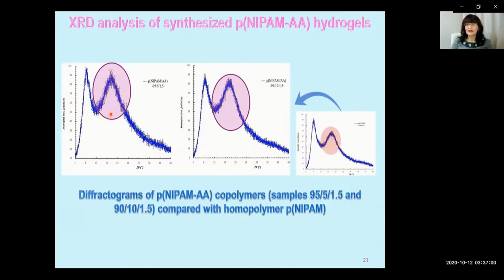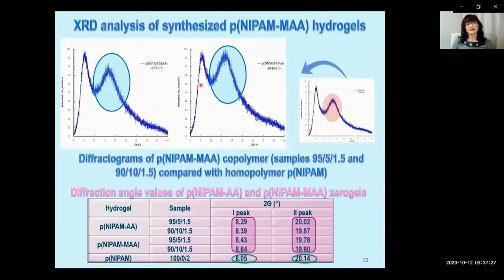All diffractograms contain 2 wide unstructured peaks. The first peak appears at a diffraction angle around 8 degrees. The fundamental wider peak appears at about 20 degrees. Similar diffractograms are seen for poly(N-isopropylacrylamide) co-methacrylic acid hydrogels, and diffraction angle values of both xerogels are noted in the presented table.